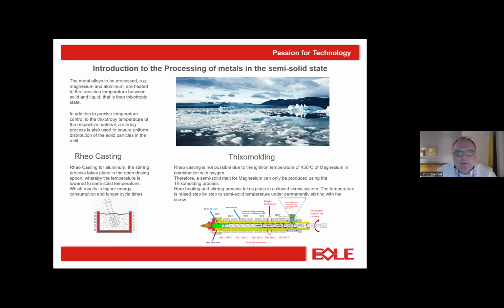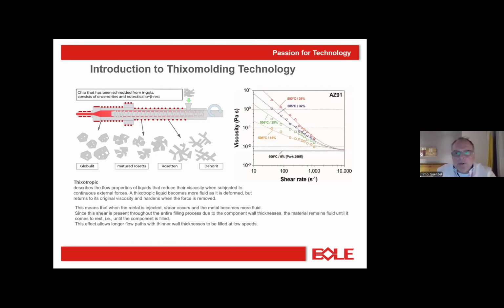We bring the material to a transition temperature, and then we stir or slurry this material. You can do this with aluminum in rheocasting. This is very simple. You do it in a ladle, but when you do magnesium in a ladle and want to make a slurry, that is very dangerous because of the temperature. Here we use the screw to make a slurry. As Marco explained, with the transport of the chips from the feeding zone along the screw to the front area, we change from the dendrite status to the globular status.